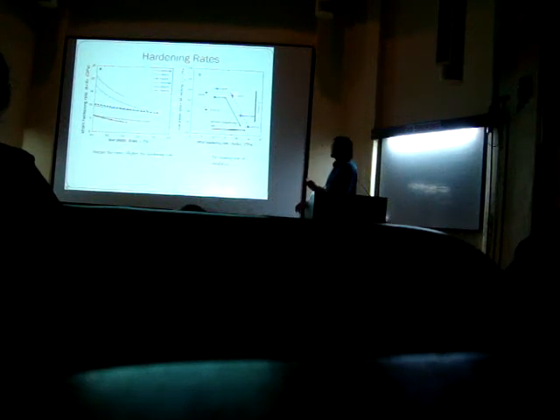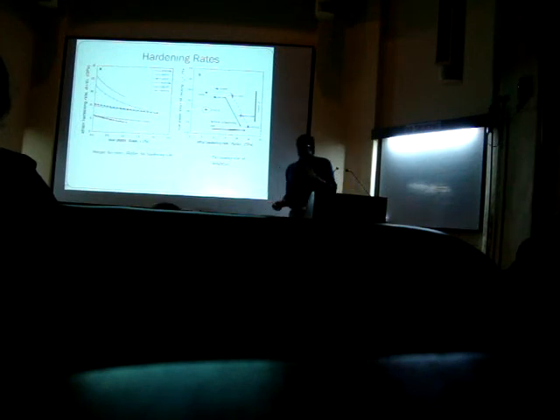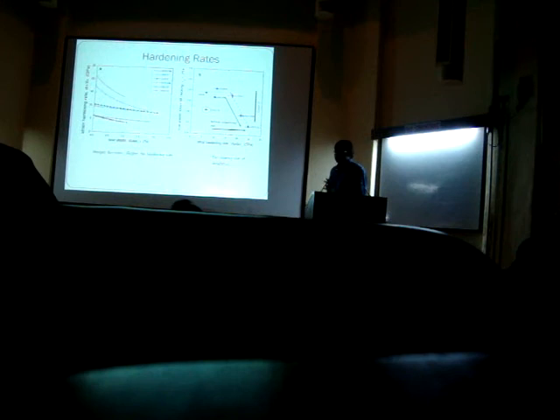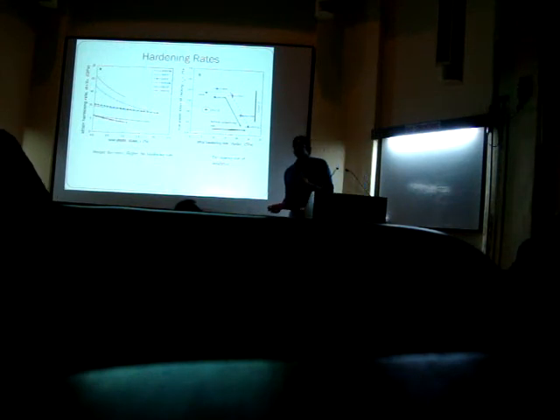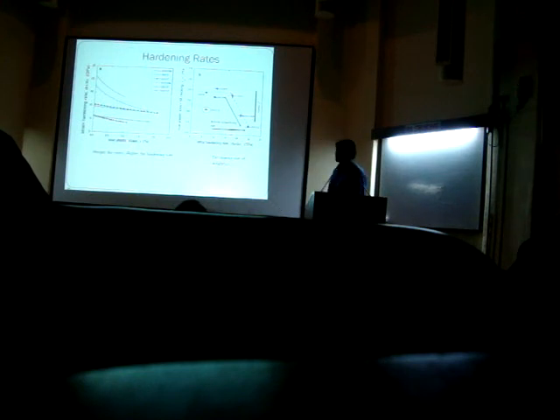You see that alloys which have the highest initial hardening rate also show the minimum amount of ductility. The forged alloys in both the cases show a very good amount of true plastic strain before necking. But when you consider the arc melted alloys of DH1, because there is a microstructural influence, they have a very low amount of ductility. So if you increase the strain hardening rate, your ductility actually goes down, which is the crux of the story. And this is very different from crystalline alloys, where if the strain hardening rate is higher, you generally encounter instability at a later point or at higher strain.